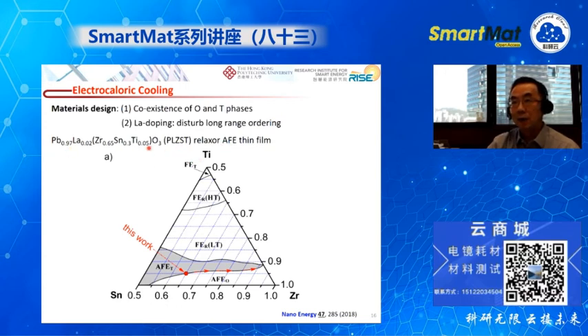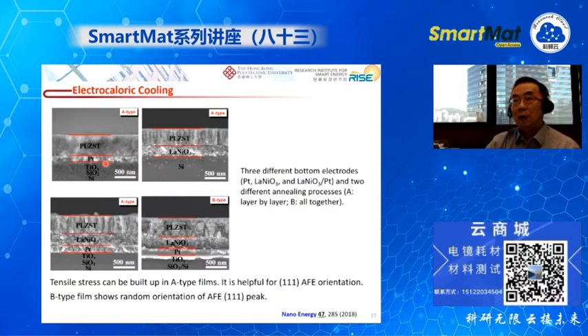So finally, the composition of the material is this one. Then we deposited this material on different bottom electrodes, such as platinum and lanthanum nickelate, and a combination of lanthanum nickelate and platinum as the bottom electrode. And we also adopt two different types of annealing process.